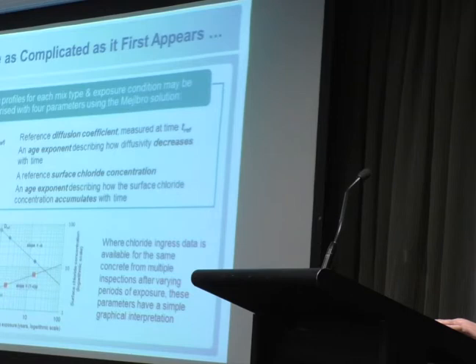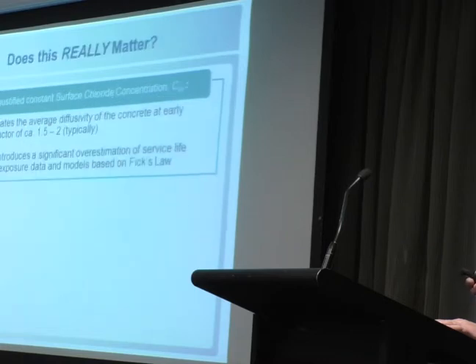It's not quite as complicated as it seems. It is still saying that you can characterize your concrete by four parameters: a reference diffusion coefficient, an exponent that tells you how the diffusion coefficient decreases with time, a reference surface chloride concentration, and an age exponent which tells you how that increases with time. And providing you have a time series on your chloride profile data, they have a simple graphical interpretation. So you can just plot them on a graph and obtain the solutions that way.